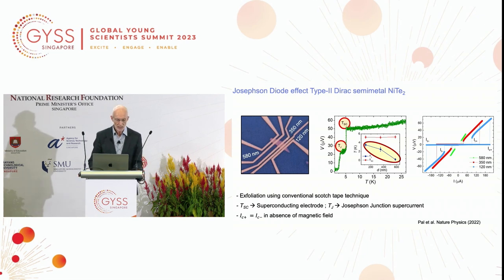Well, it turns out normally, this you can see in this picture, we've taken this little irregularly shaped flake, it turns out it's a 2D material. It's nickel ditelluride. It's a very special material, which is a Dirac semi-metal. It has surface states which are spin polarized. And then on top of this, we create these wires. These are formed from niobium, a conventional S-wave superconductor. We pass current into this non-superconducting material. It becomes superconducting by proximity.